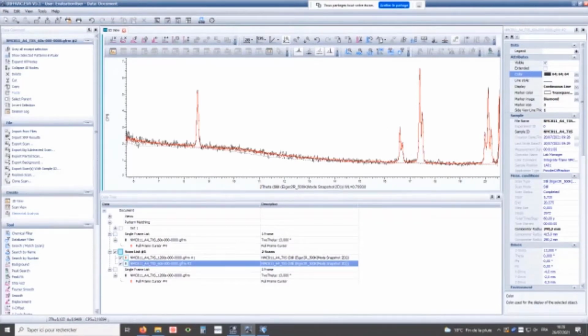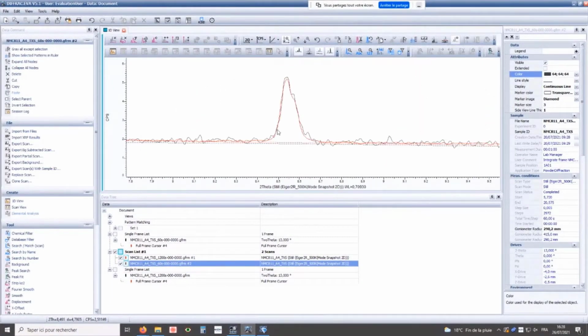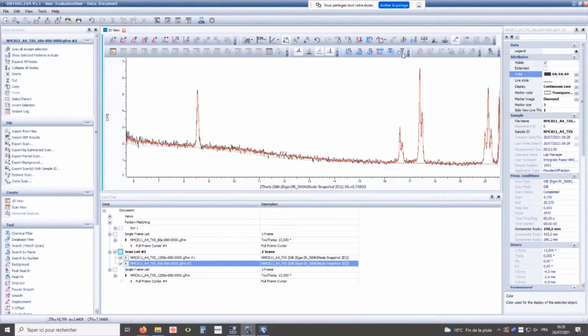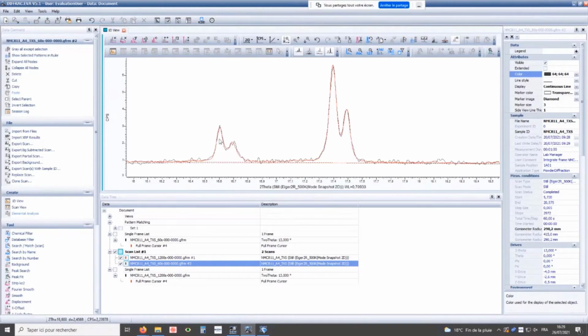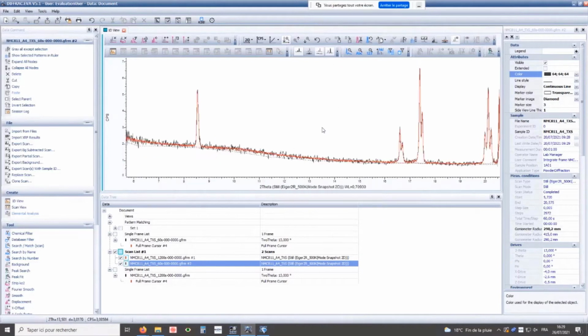So obviously, in 20 minutes, the gain in terms of noise is very, very big. But still, we can see that the peaks here, even measured within a minute in black, are well defined with a nice intensity to noise ratio, allowing us to do at least profile matching of our powder patterns and checking the evolution of the cell parameters in a very fast way.